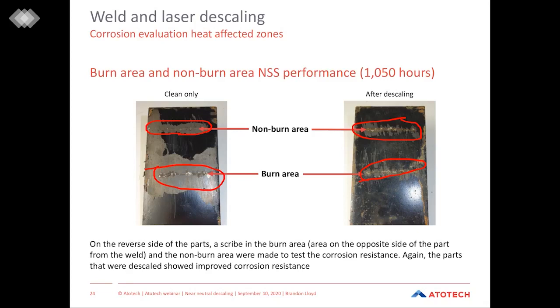As we move over to the part with Uniprep AC added to the process for descaling, you can see that the non-burn area is showing some improvement, but not a lot in comparison to the burn area. But we see that for the burn area, as compared to the clean-only part, we see a significant improvement. And what we also see is the fact that the non-burn area and the burn area of these parts are exhibiting almost identical performance, showing that the addition of the descaler is really improving the overall part performance.